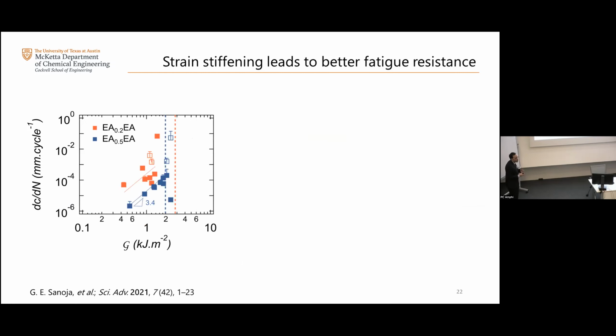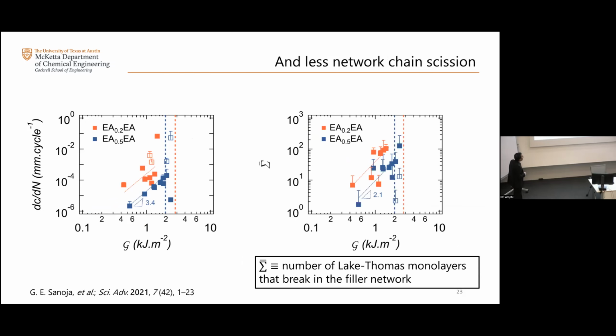And again, the macroscopic observation is already interesting on its own, in my viewpoint. For example, what you see here is that the system in red is actually tougher, meaning that it's more resistant to crack propagation when you apply monotonic loading, but it actually behaves poorer in fatigue. It's not as fatigue resistant as a system that is more brittle. Okay, so we thought that that was interesting on its own because it's showing us that toughness, again, is not a good metric for fatigue resistance, and systems that are tough are not necessarily good under cyclic loading. And the second observation, which is more molecular in nature, is summarized in this plot.